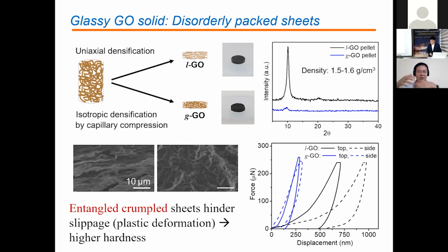If I borrow this structure, if these are two-dimensional sheets, and you introduce some single nanotubes, which by the way you can do by just sonicating graphene oxide and nanotube powders together, because graphene oxide can indeed disperse them. But in this case, it would be difficult to generate just individual tubes. You might get bundles of tubes, but that might be okay for the microstructure. If you do that, the nanotubes are basically stitching up these soft sheets.